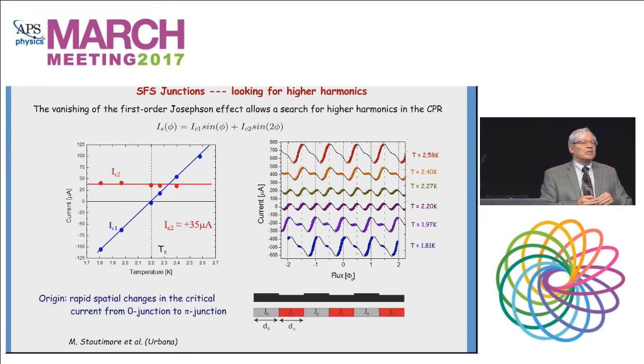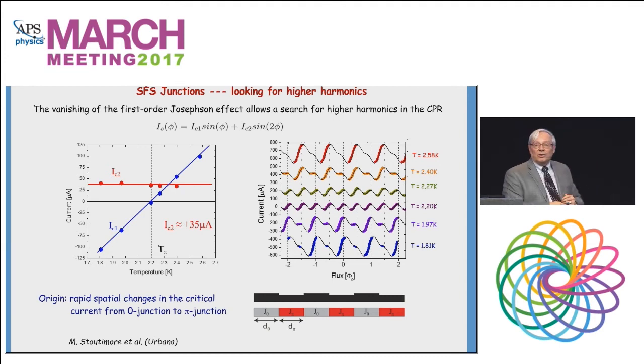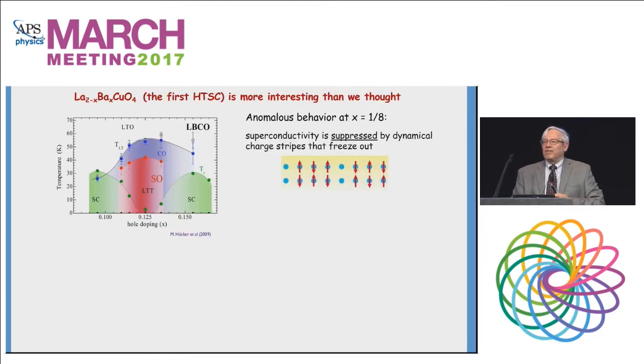And this can come from rapid spatial modulations in the order parameter. In this case, they come from the fact that you're near this 0 pi transition. And so if the barrier thickness varies a little bit, parts of the junction are 0 junction, parts are a pi junction. And so what happens is, in this case, the first order Josephson effect cancels out, and you're left with a sine 2 phi term. This has been used very effectively recently.